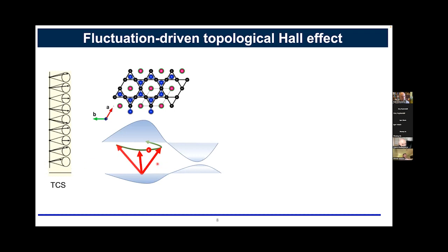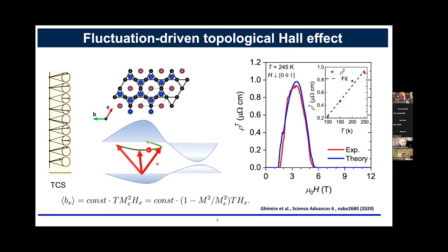Kind of try to visualize it, and that generates this third vector component, and then comes the scalar spin chirality, and that gives rise to the topological Hall. Igor, who is here in the audience, developed a small theoretical model for this. And then the calculated topological Hall matches pretty well with the measured topological Hall. And that's why we really believe that this is coming from fluctuation-driven phenomena. So that's a fluctuation-driven phenomenon in the topological Hall effect in YMn6Sn6.